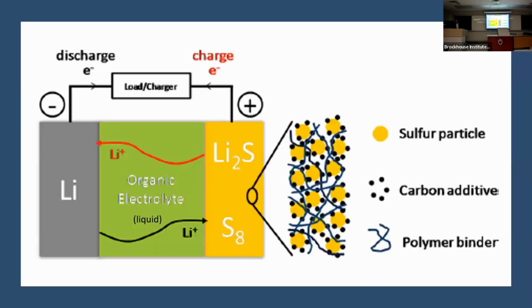Okay. Now the lithium-sulfur battery is actually exactly the same architecture. It's called lithium. It could have carbon or some other host, but pure lithium, and it has sulfur as the other electrode. And it has a liquid electrolyte with organic solvent containing a lithium salt. And the architecture is exactly identical to lithium-ion batteries. One advantage of that, existing assembly lines can very quickly adapt to this one. So if you have a lithium-ion battery assembly line, you can incorporate lithium-sulfur into it. So there is no development cost for making a new type of assembly line. So that's very, very key for moving forward, because all the available infrastructure could be utilized.